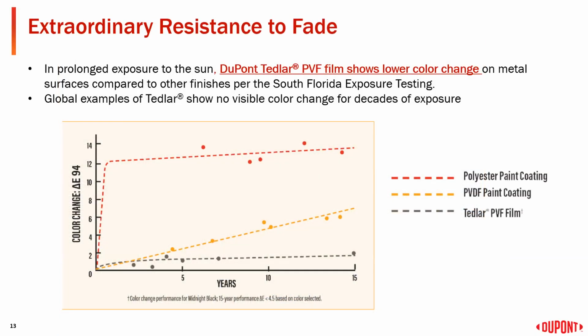Extraordinary resistance to fade is one of the strongest performance attributes about Tedlar, is that it basically doesn't change color over time. So this chart is showing you a delta in color over 15 years of Florida exposure. The Tedlar is the gray line at the bottom. So you can see there's about 1 degree of color change and then nothing for 15 years. You'll see PVDF kind of steadily will change over time. And then less expensive coating systems like polyester, SMP will change rapidly in those first few years and then kind of flatten out. That's really important when there's damage and you want to just replace one section instead of having to replace the whole roof. That makes a big difference. Exactly. Yes, you can feel really confident that you're just going to have to replace the damaged area.